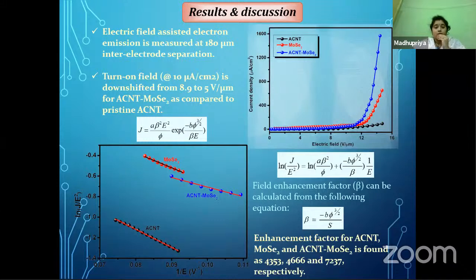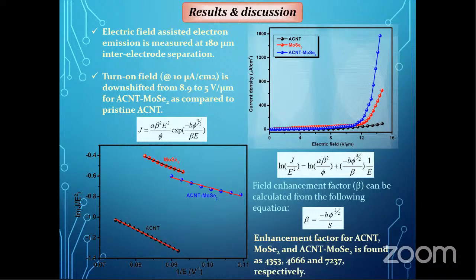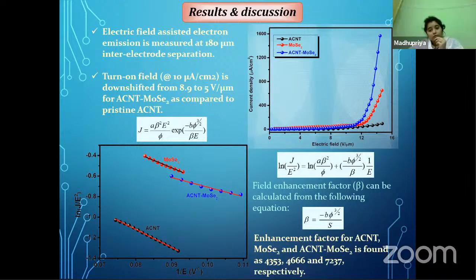After that, we have measured the electric field assisted electron emission of these three materials, measured at 180 micrometer inter-electrode separation. The current density versus electric field is plotted in the graph, and it has been found that our ACNT MoSe2 composite heterostructure shows better results than the other two counterparts. The turn-on field, measured at current density 10 microampere per centimeter square, is downshifted to 5 volt per micrometer for ACNT MoSe2 compared to ACNT, which is around 8.9 volt per micrometer.